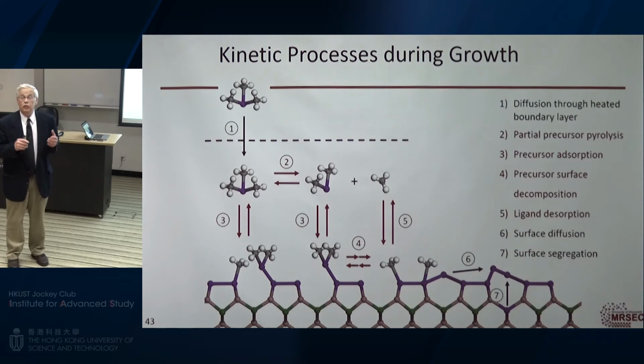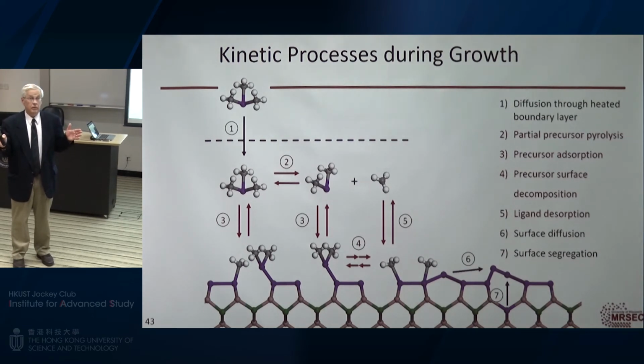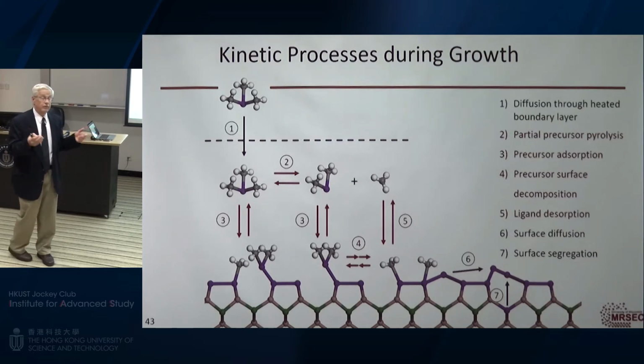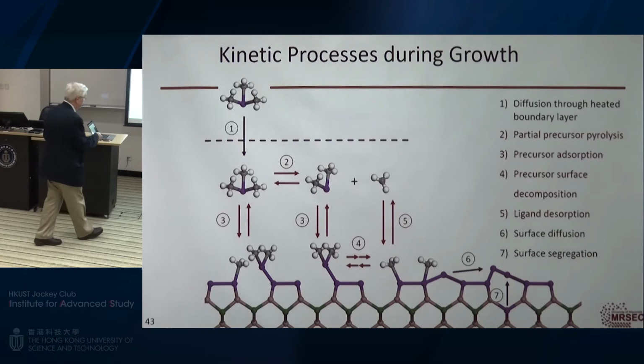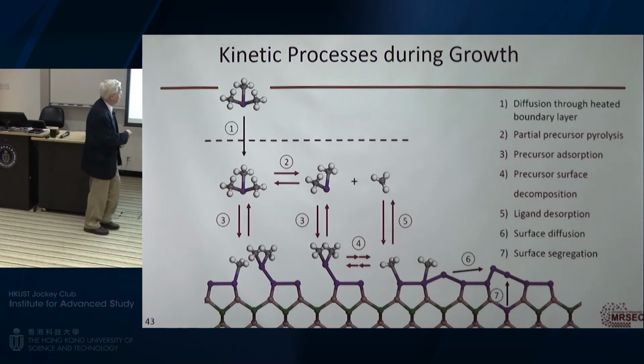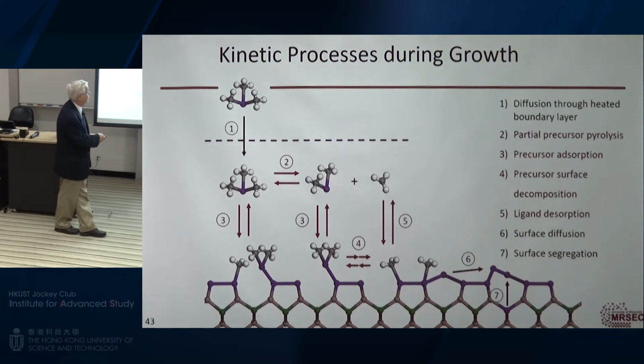So one of the things that we notice is that I can grow some gallium arsenide bismuth, but then the growth rate stops. All right? It won't grow anymore until I stop trying to put bismuth in the system. So some chemical reaction is happening, or some condition of the surface, that allows us both to make a metastable alloy, as well as controls the incorporation.